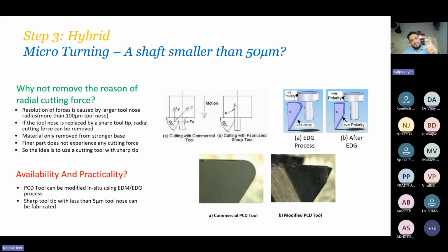Let us machine up to 100 micron through turning. Then, because our machine's spindle has the capability of doing EDM, let us switch on the EDM and do wire electrical discharge grinding. It is an EDM process. And long story short, this nose radius became this. So the nose radius was turned down to 5 micron. So it's almost a sharp edge. Okay, 5 micron nose radius.